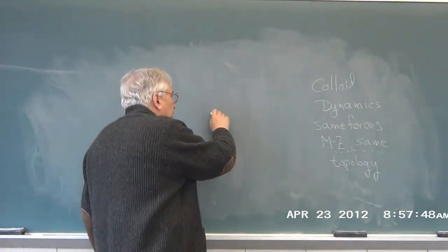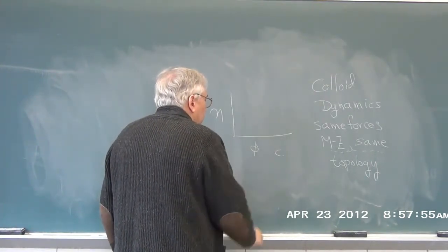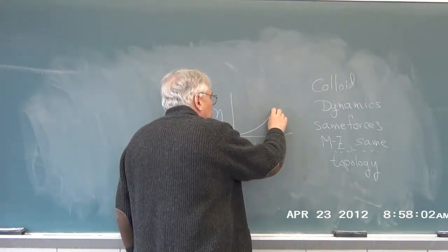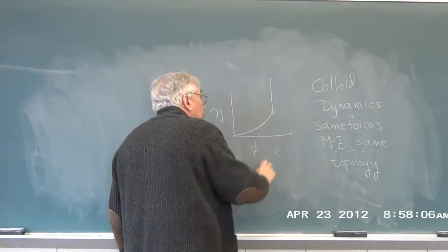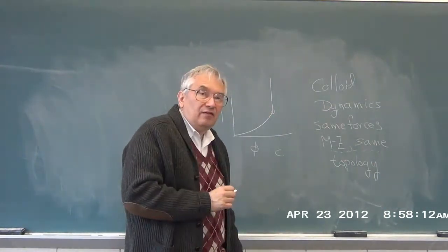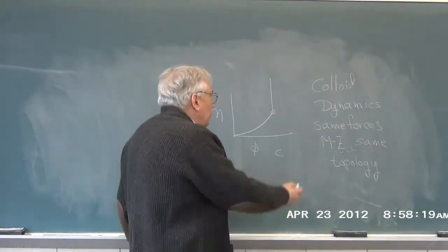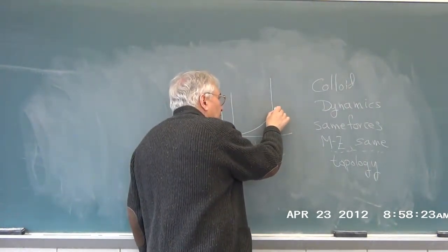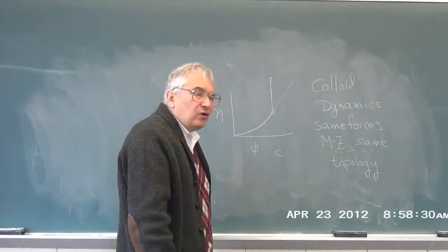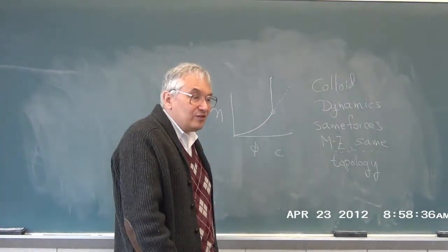And so, for example, we can look at viscosity versus sphere volume fraction or versus polymer concentration. For colloids, we see a stretched exponential that comes up, and then there is a completely sharp crossover to a very steep power law. This is solution-like, melt-like behavior. It's seen for spheres, so it has not a lot to do with topology, with one minor exception. For polymers, the curve just keeps on going. For spheres, there is a sharp upwards turn. You should realize that the concentration and viscosity axes may be very different for these different systems.